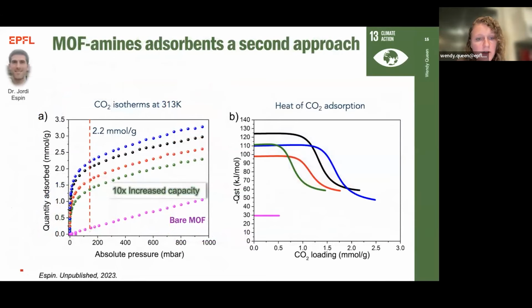So from there, we've done some other modifications to try and further optimize the amount of CO2 that our materials can absorb. And so here I'm showing you again the bare MOF. We've made other amine modifications, and we've been able to get our adsorption capacity at about 0.15 bar up to around 2.2 millimoles per gram. Now, before I told you the previous adsorbent was about 1.5. Here you can see the binding energy associated with the parent MOF and then the amine modified materials. Here in this case, we're going up to about 125 kilojoules per mole in terms of the binding energy.